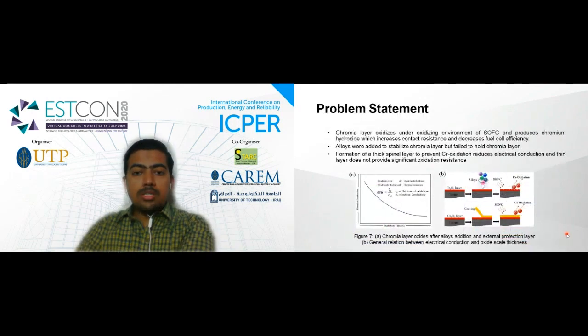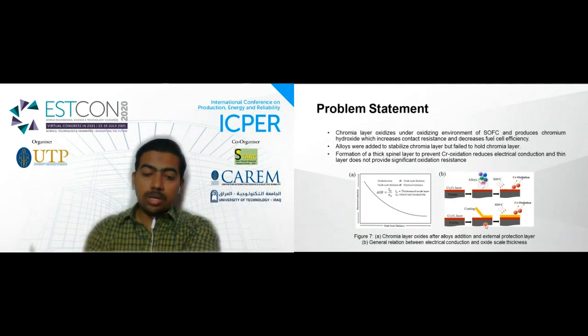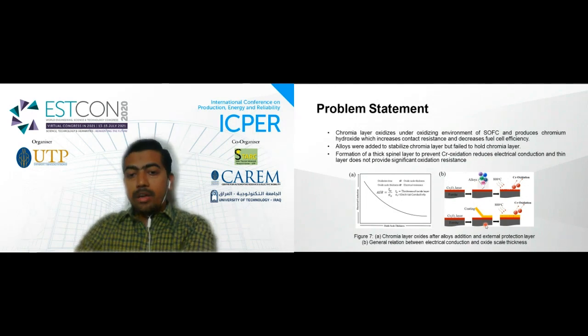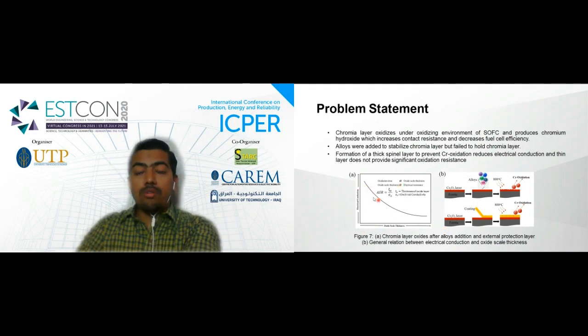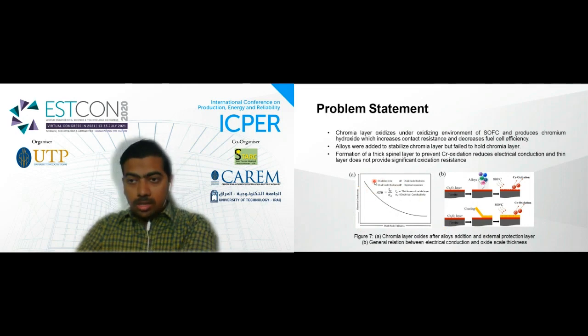So the problem statement is that every steel has the chromium layer. Different types of alloying elements have been added, but they fail to reduce chromium oxidation. Another method used by different researchers is to fabricate a thin coating layer over the surface. But if we increase the thickness of the oxide layer, it decreases electrical conduction according to this formula. So if we increase the thickness of the oxide scale spinel layer,